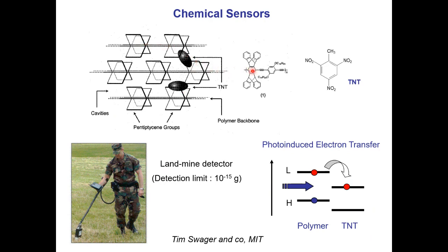So basically you have a polymer, a conjugated polymer, which is very, very emissive. And there are side groups making kind of channels for small molecules to go inside the molecules. And so when the polymer is in the pristine state, you excite the chain, you get the HOMO-LUMO excitation, and you have a very efficient light emission in return.